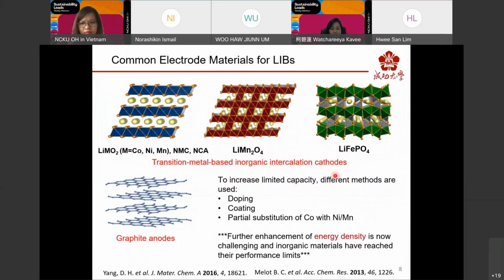So over the years, there have been a lot of efforts on the transition metal-based cathodes, such as LiCoO2 in particular, by doping, coating, and partial substitution of cobalt with nickel and manganese in order to optimize the performance of the commercially available lithium-ion batteries, and also to increase the practical capacity, which is now much lower than the theoretical value. However, further enhancement of energy density from these traditional materials is becoming more challenging, and it seems that inorganic materials have reached the critical limit in their performance.